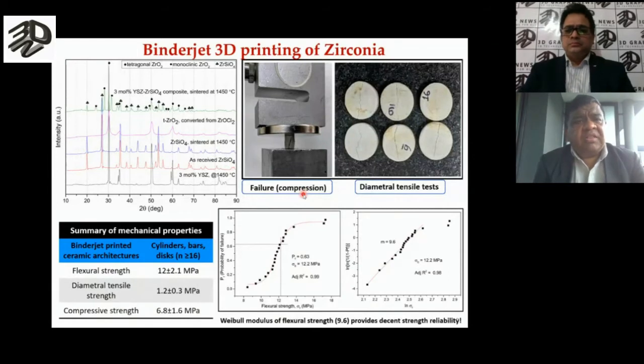Now we are trying to understand whether binder-jet 3D printing, the same technique that I have shown you in the last few slides, can be adopted for zirconia. And it was not an easy thing. It was in fact a nightmare to do binder-jet 3D printing of zirconia. We have tried several approaches, including infiltration of the zirconia printed body with zirconia precursors. We have used different stabilized zirconia, 3 mole % stabilized zirconia or magnesium stabilized zirconia.